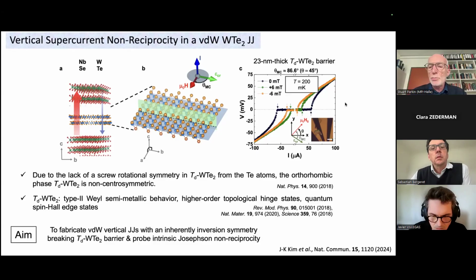And if you look at the top on the C, you can see the voltage versus current curve. For the case of 0 millitesla, that's the black curve, then the critical current flowing right and left are identical. However, in the presence now of a 6 millitesla field, but now we can apply a field in the plane of this van der Waals material, which is vertical, which is orthogonal to the supercurrent, which is now flowing vertically. So now we can rotate that field in any direction in the plane of this tungsten ditelluride.